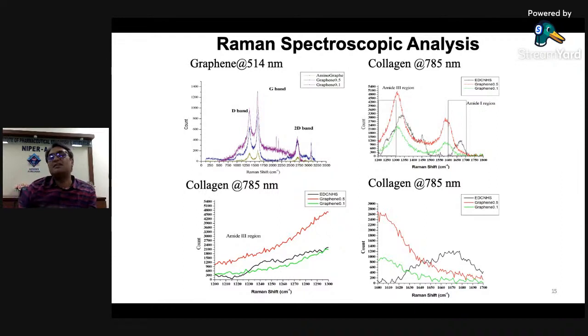For that, we checked the graphene spectra in Raman spectroscopic analysis, and we found there is not much difference in the graphene. All the graphenes incorporated at 0.5%, 0.1% are same, so there are no deviations between the groups. However, when we looked at the collagen in Raman spectroscopy, we found there is an uptrend in the regions of amide 3 and amide 1.